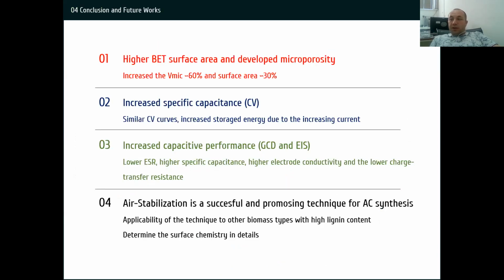As a summary, the new approach that can be applied to biomass with high lignin and hemicellulose content, thermostabilization, led to higher BET surface area and to development of microporosity, almost 60%. The specific capacitance has increased at higher current densities. The stored energy increased with the increasing current, and in the thermostabilized sample, lower ESR and higher electrode conductivity were obtained compared to only chemical activated carbon, APC sample.